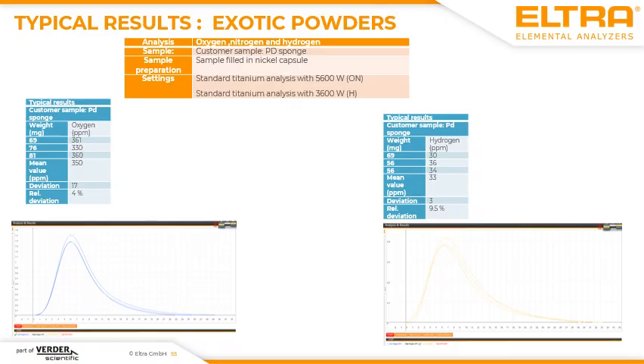Here we had a manufacturer of precious metals, and they sent us some palladium samples. And like the steel sample, you can just fill in the sample in a capsule and analyze it. And for this kind of precious metal, it was necessary to not only apply the sample to a capsule, but for oxygen analysis, we have to use a high sample amount, power of approximately 5,600 watt. So then the analysis of precious metals is safe in the analyzer.